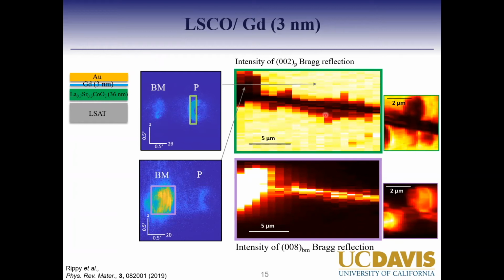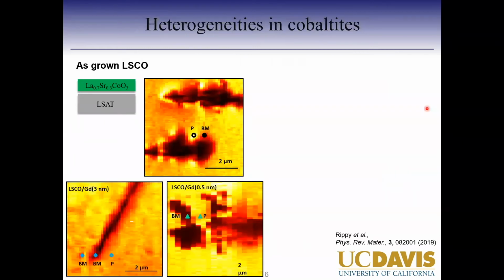So from these filaments, we can zoom into a smaller section and look at what's happening at these regions. We start to see a very complex distribution of brownmillerite and perovskite at these 1 micron length scales, where you have strong brownmillerite here, perovskite here, and a transition region where both phases are present in the material. We can do this experiment for different thicknesses and different samples. We did this even for as-grown LSCO, which should be fully perovskite. Even there, we see some small pockets of brownmillerite, compared to the other 2 samples.